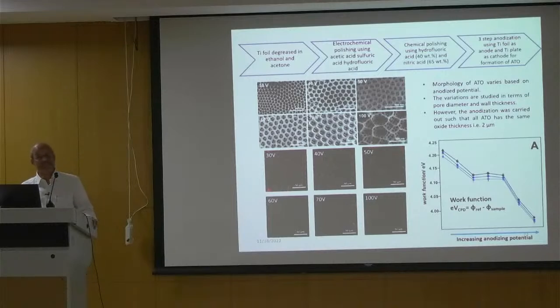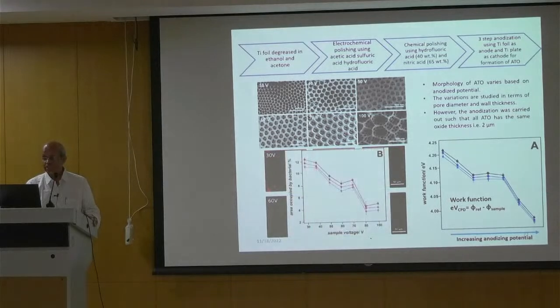It produces different thicknesses of titanium oxide. The moment the thickness changes, the Fermi level also changes. So a charge transfer process took place, and this is going to explain our hypothesis. The area occupied by the bacterial percentage is also seen here, and there seems to be a small correlation between the increasing anodizing potential, the area occupied by the bacterial specimens, and the work function.